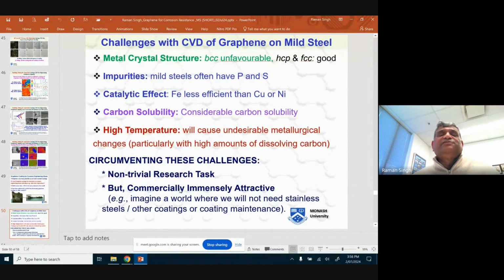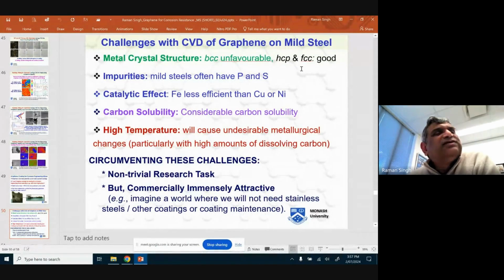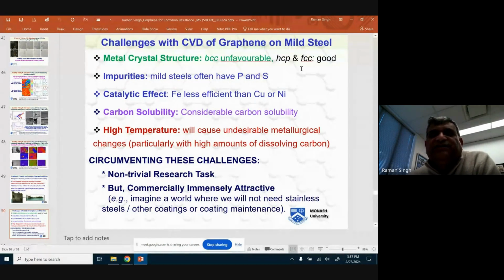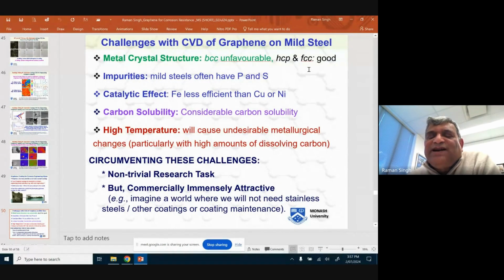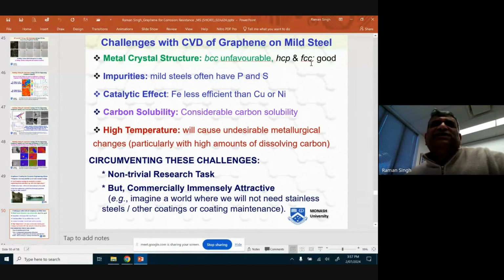What is the challenge? If there are some metallurgists in the gathering, they will understand that iron or steel at high temperature, like 900 to 1000 degrees Celsius, has a face-centered cubic structure. Why 900 to 1000 degrees Celsius? Because that's the temperature for CVD, chemical vapor deposition. But iron and steel is body-centered cubic at room temperature. Why I'm talking about crystallographic structure is that the face-centered cubic structure has 100 times greater carbon solubility. So at high temperature, lots of carbon will dissolve in the face-centered cubic iron lattice.